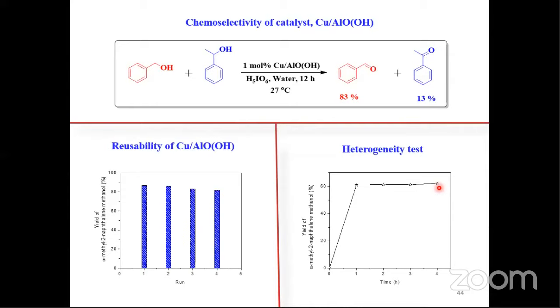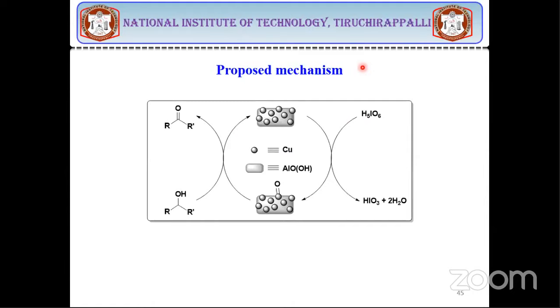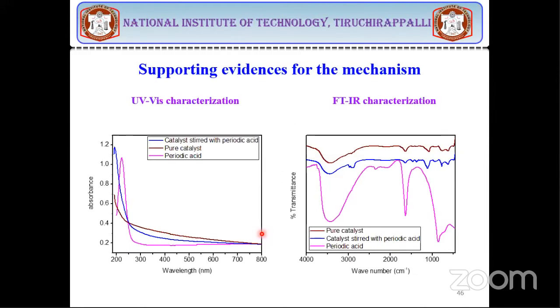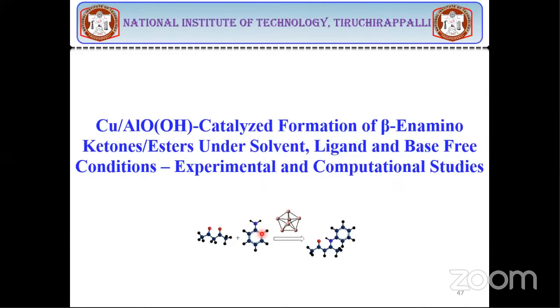It means there is no metal in the solution, which indicates there is no leaching of copper from the surface of the boehmite. So the reaction here is truly heterogeneous in nature. At the same time, we have very good selectivity. And of course, the reaction proceeds via the formation of copper oxo species. And we have detected the presence of copper oxo species in the reaction medium by means of UV-visible and FTIR techniques during the reaction.